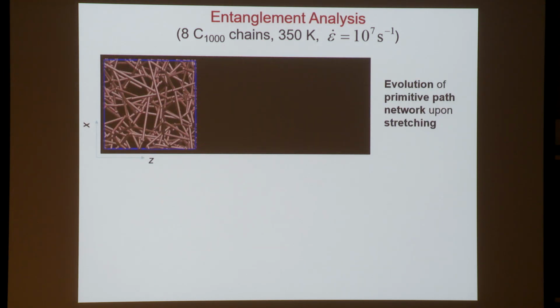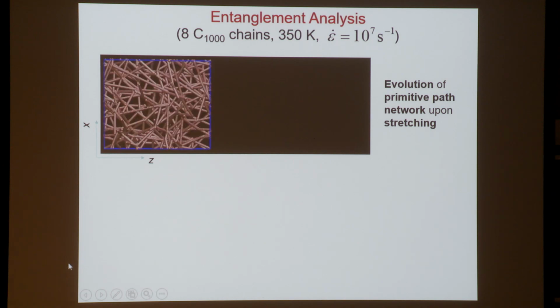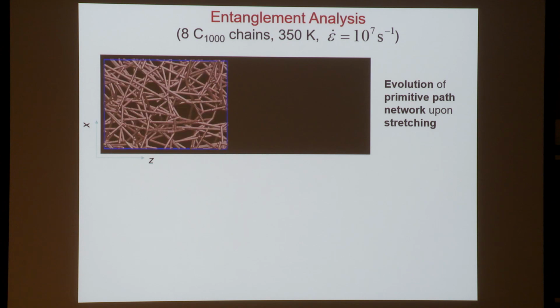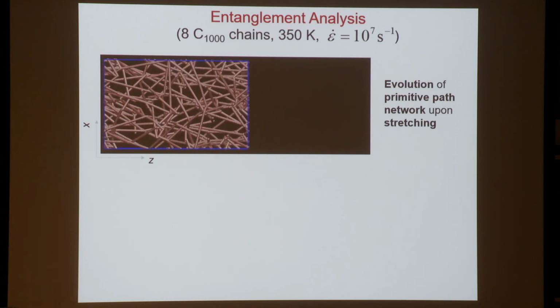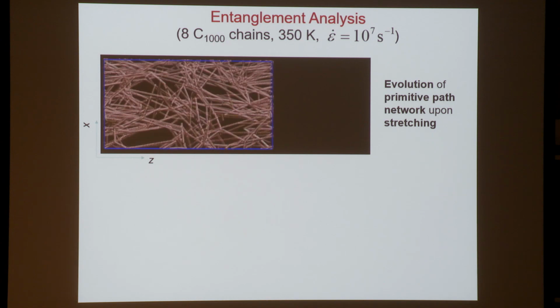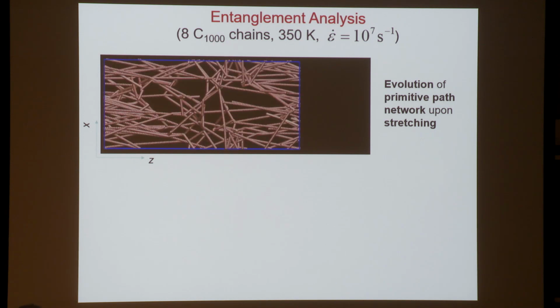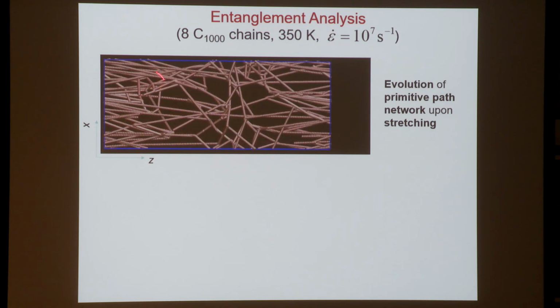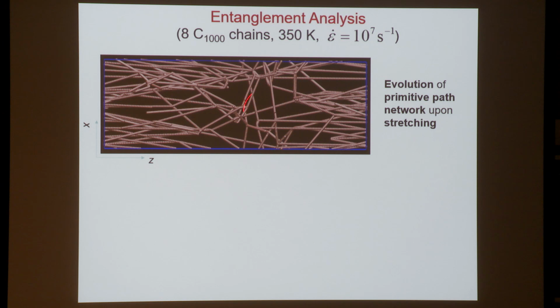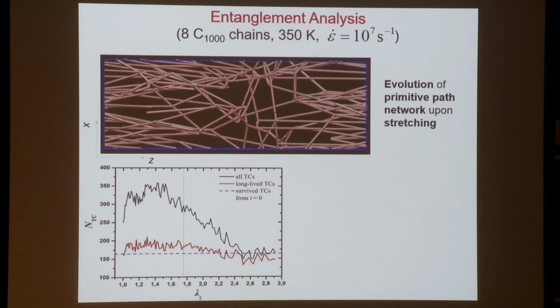At the same time, one can also track how the entanglements in the system evolve upon the emergence of these ordered regions. Originally, the system has entanglements throughout, and these kinks are the entanglements. But then when it starts crystallizing, you will see that the primitive paths become very elongated where the crystalline regions are. The kinks are pushed into the amorphous region, and one can even count the entanglements and see how they behave against the stretch ratio. This black line is the total number of entanglements, because some entanglements really flicker. I mean, they are not permanent, whereas some we classify as long-lived because they survive throughout the simulation.